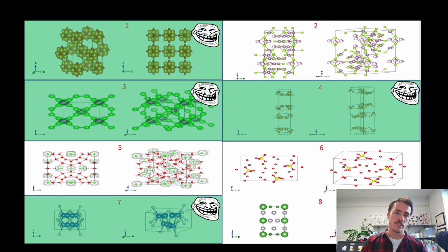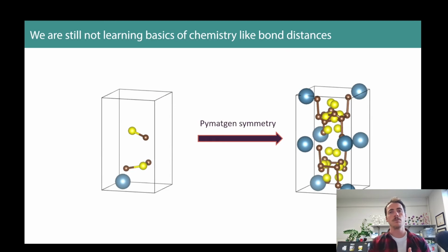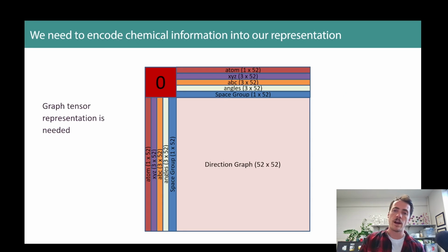If you look at the ones there, there are some issues because there are atoms on top of each other. That's the main problem. If you look at our representation, we learned the basis, we learned the unit cell size, but then we relied on the space group to go from the basis here on the left to the fully populated crystal structure where all the atomic positions are noted. And in doing that, you got atoms on top of each other with crazy distances. It was really bad. And the only way around that was with a new representation.